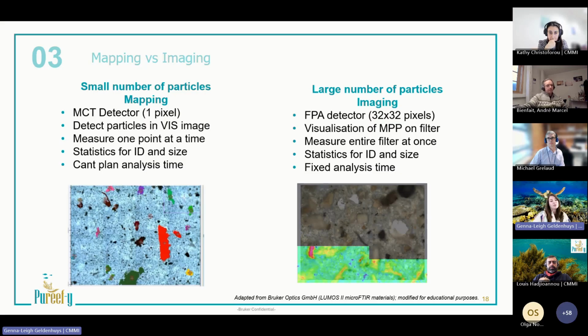What's also important to note here is that there's no way to properly plan your analysis time, as it depends on a particle-by-particle approach. With imaging, on the other hand, you need an FPA detector, and you measure the entire filter at once without missing any particles. This is because evaluation is based on hyperspectral images. Remember, that's millions of FTIR spectra, and it's based on the chemical info, as opposed to the mapping, which is based on the visual image itself.